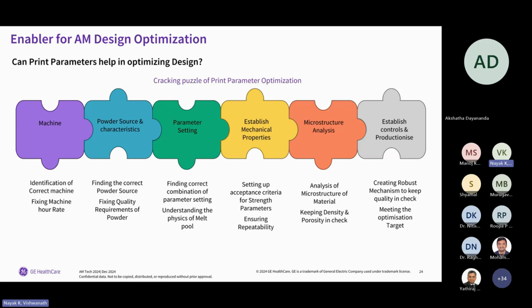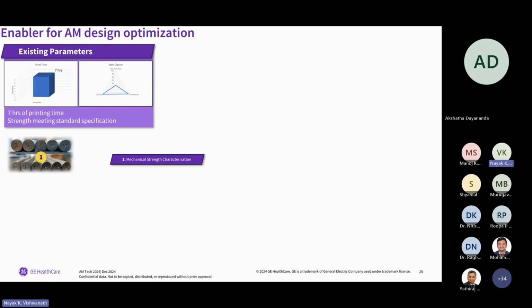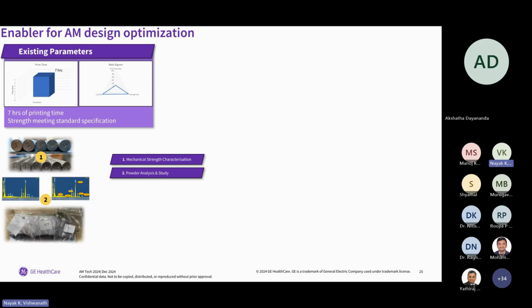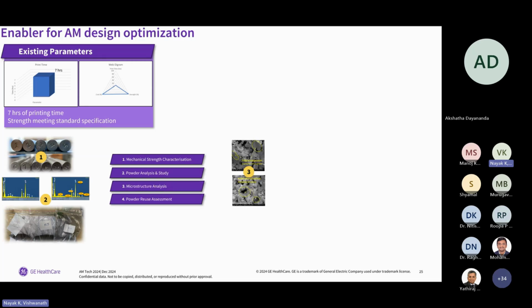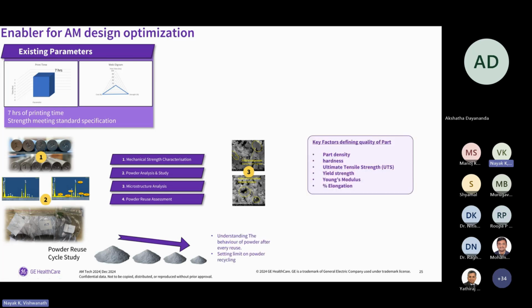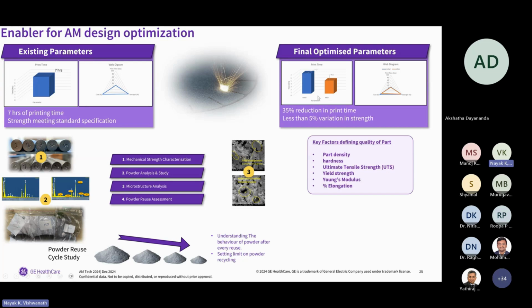Parameter setting is one of the most critical aspects, because it determines how the melt pool will be and how this particular metal behaves when it fuses. There are more details as we go. But another important thing I wanted to say is that in one case we had almost 7 hours of printing time, and it was definitely meeting the strength. But then we optimized the parameters a lot. We studied its behavior over a period of time, and came up with a better powder reuse cycle study. Looking at all of this, we could optimize the parameters to less than 4 hours.